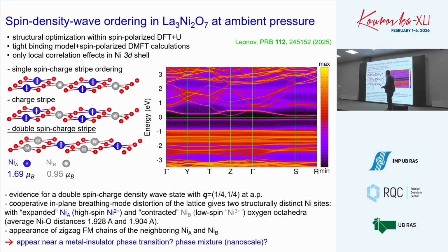We still have some localized spin, some kind of strongly localized paramagnetic and nearly metallic sites, and these are somewhat localized and nearly insulating. It is some kind of unusual electronic state, and in total it becomes somewhat of a bad metal. I would say the system is at the verge of the metal phase transition, but most probably it is somewhat metallic. But yeah, it really depends.